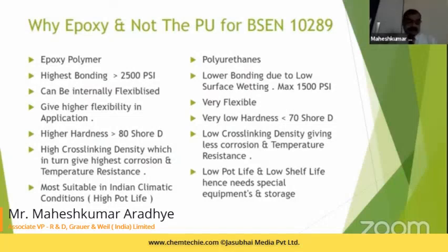So it is the most suitable coating for Indian climatic conditions, because it has a high pot life. The pot life is almost 30 minutes at 40 degrees C, which is a huge pot life, in which you will be able to cover most of the pipelines.